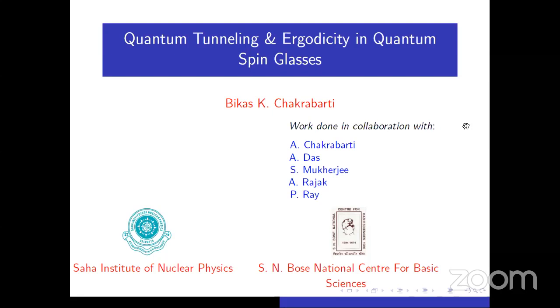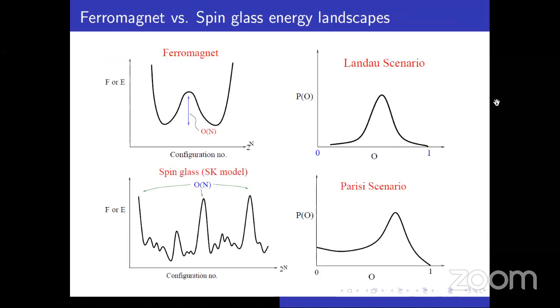I was discussing that in a many-body system, this is the typical scenario where you have one ground state and it's a kind of double well situation in the energy or free energy landscape. But you can have frustrated random disorder, like in spin glass, where you cannot transform away the disorder. If you could transform it away, you would go back to the ferromagnet scenario. Otherwise it will be spin glass, where you have a rugged landscape and the system becomes non-ergodic because you have a large number of barriers which are of the order of the system size, N.